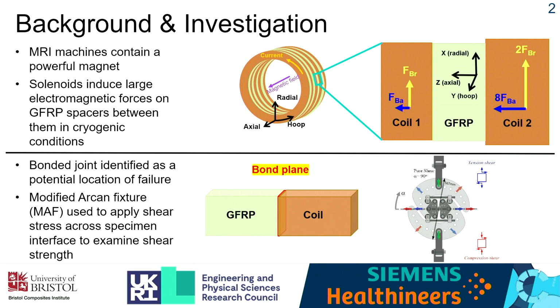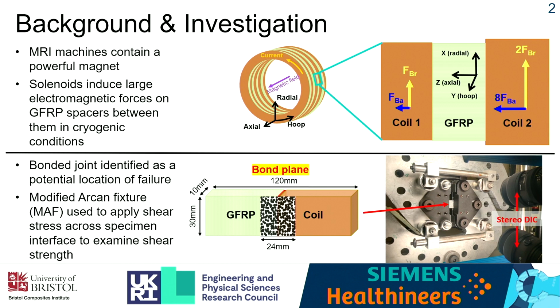I'm using a Modified Arcan Fixture, first in shear configurations, and then in the biaxial states that you would expect to find within the MRI magnet. And this is initially looking at the shear strength. And these specimens are water jet cut out of a big block of material and then milled down to remove any damage left with the water jet cutting, as it's a very difficult material to work with. And then a speckle pattern is applied to enable DIC non-contact measurements.